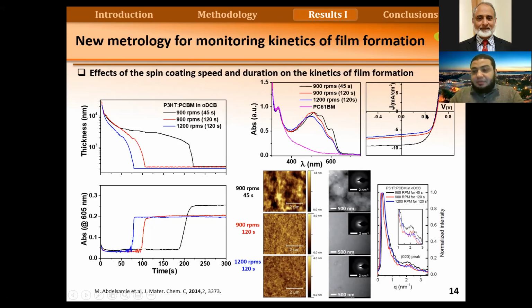As we tested the devices, we got a much higher performance for the one that was processed with 900 RPM and 45 seconds. And we could link the dynamics of film formation to the final product, and understand why this happens. This was mainly due to the increase in the dynamics of the aggregation. So the material itself has longer time to self-assemble and crystallize. It improves the crystallinity in the final film, and this also helps the donor and acceptor materials to phase separate into more pure domains.